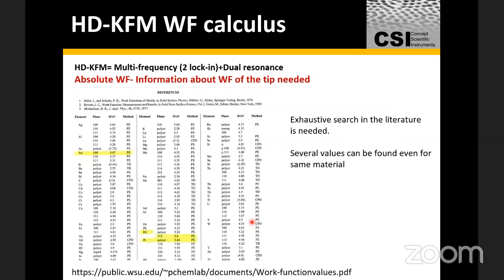And how do we really know about these work functions? These are typically dependent upon lookup tables. And as you can imagine, when you're translating a lot of these lookup tables, you have to remember that most of these values for work function that we're using here, for example some of the highlighted ones like gold, palladium, or platinum, are typically conductive materials that are used as the cantilever tip.